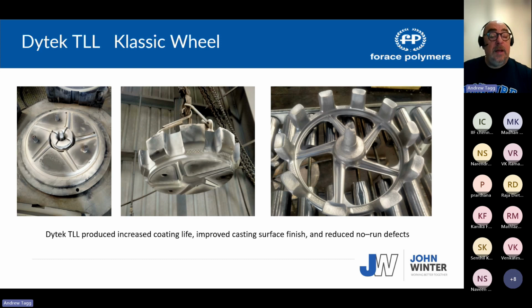And this is a classic wheel. Again, there's a coating, and again, this had a certain problem in this area. The problem with gravity die casting compared to low pressure, if you imagine on a car wheel similar, is the metal's entering here, and travels on here. So the metal entering this area is the coldest, and you have to promote directional solidification back from the feeders to the center hub. So the insulating properties of the coating are very important. And I'll show later, we introduced Dytek V in these areas where the risers are, and that helps shrinkage defects. So I'll move on to that later.